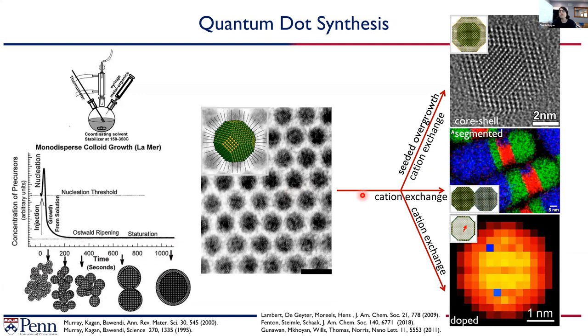So for example, you can take these particles and use them as seeds and overgrow another semiconductor on top to make core and shell structures, much like heterostructures you know from bulk semiconductors. And you can also use approaches first introduced by the Alivisatos group to use cation exchange, where you can replace the cation, for example, with a different cation that can also be used to grow core shell structures. You can make what we call segmented structures, side by side. And you can also, by controlling the concentration and the other ligands in the solution, use them to dope these quantum dots.